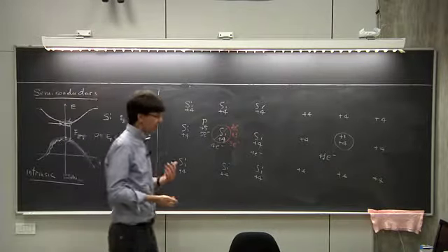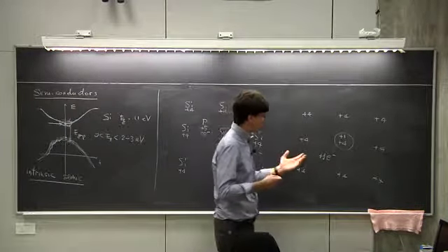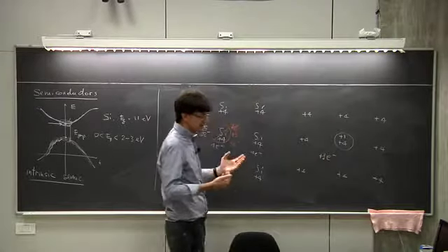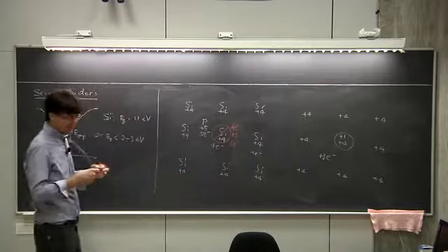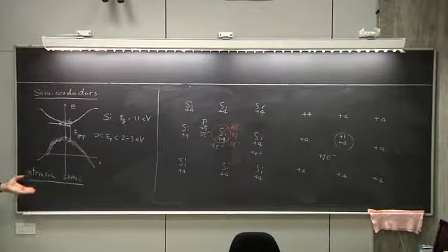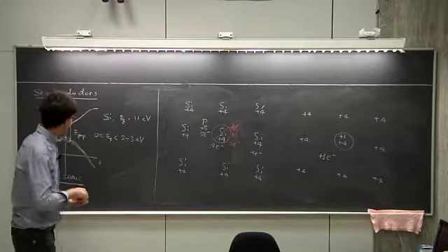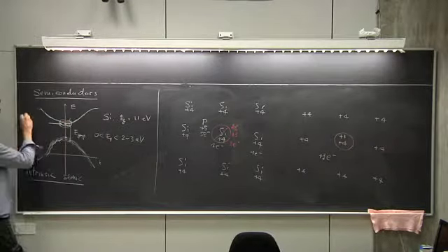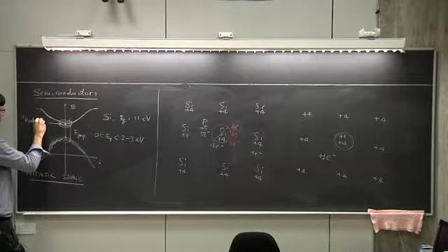Of course, you do your necessary scaling due to the fact that these two objects don't exist just in vacuum like the hydrogen problem, but exist embedded into a charge density composed by the electrons and the nuclei that are already there in silicon. Okay? So this is just to say that the position of these states here can be understood based on a quasi-hydrogen atom theory.